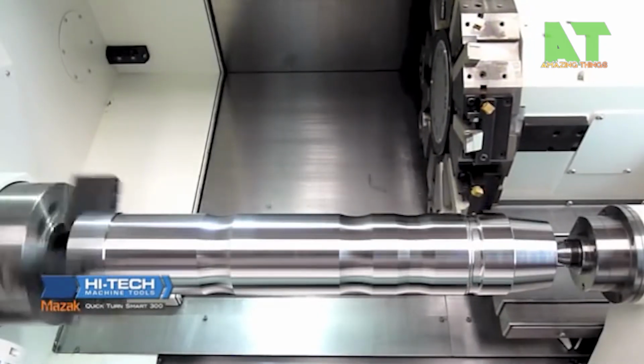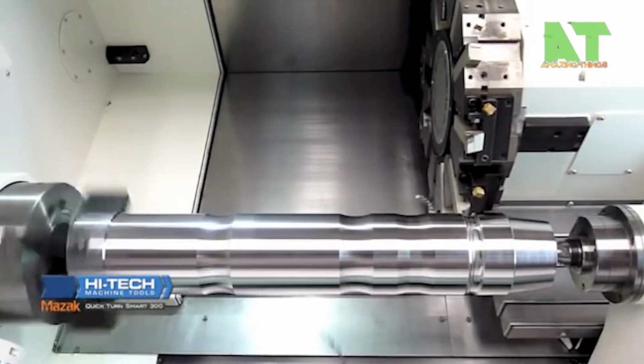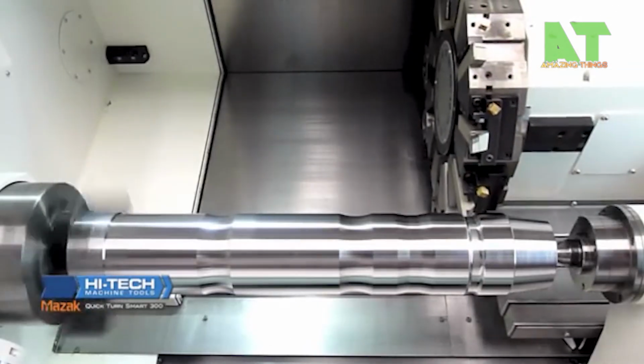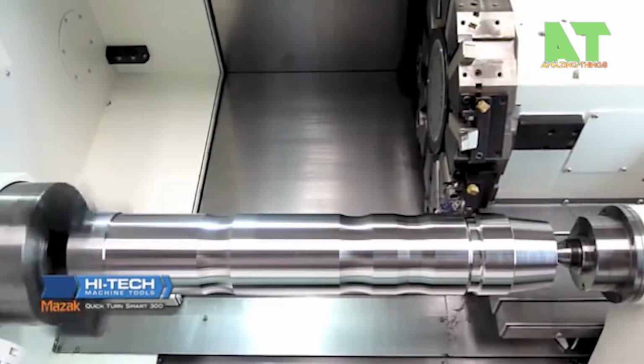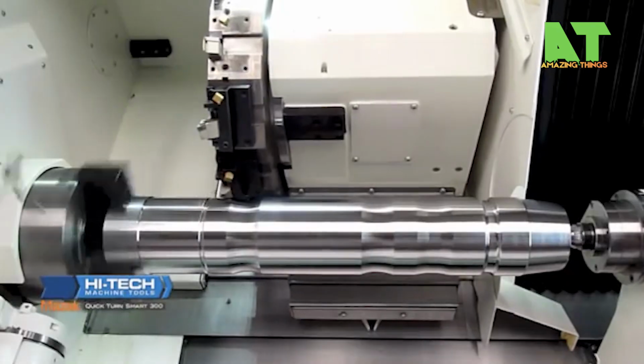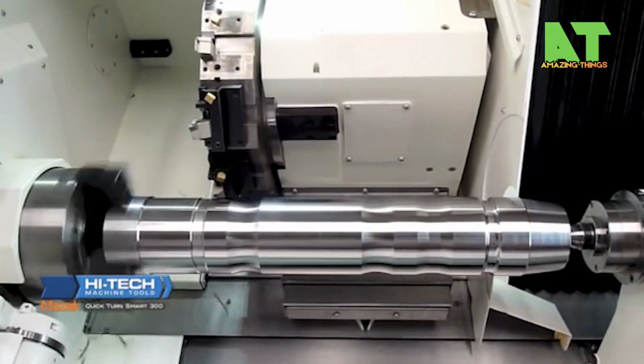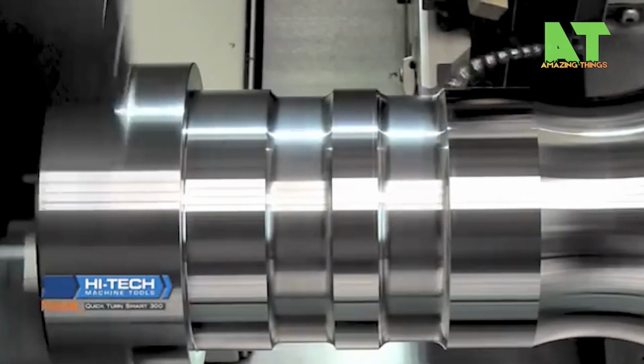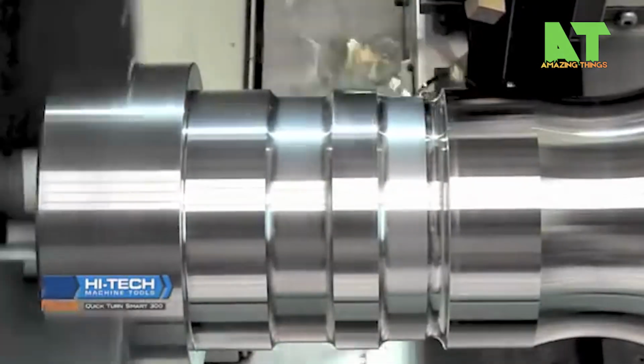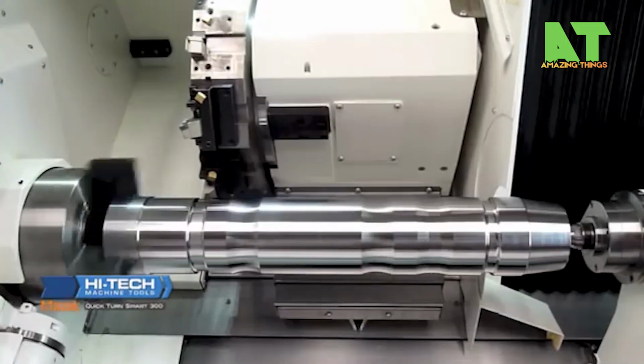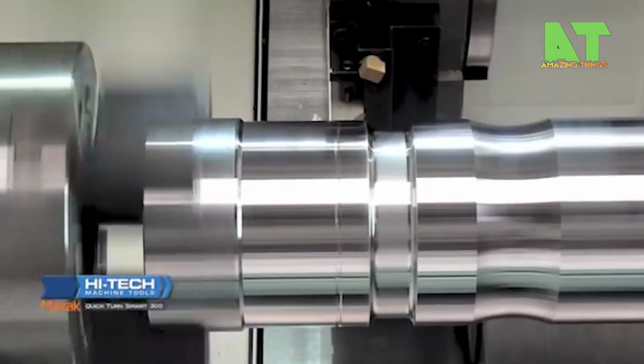After roughing, the machine switches to finishing tools automatically. The turret indexes to the next station in under a second. Finishing passes take lighter cuts, achieving surface finishes measured in microns. The driveshaft's journals, the precision ground-bearing contact zones, must be turned to tolerances as tight as plus or minus 0.01 millimeters. That's roughly 1/5 the thickness of a human hair.